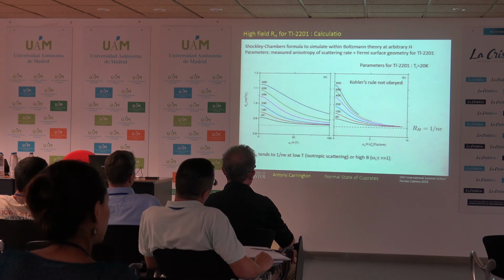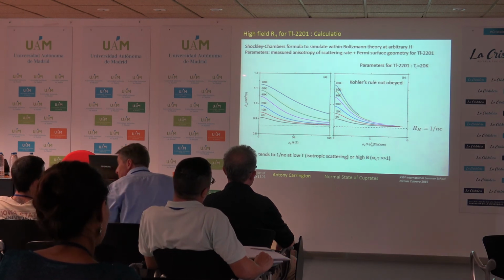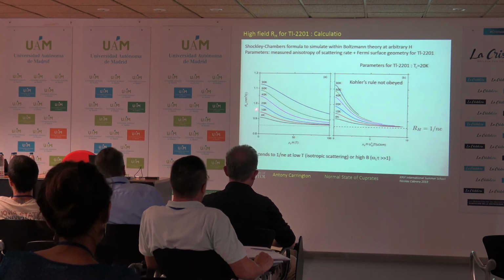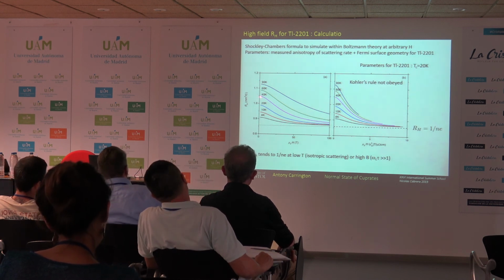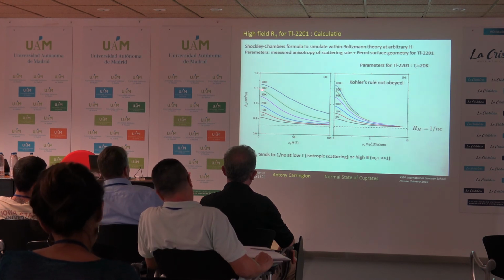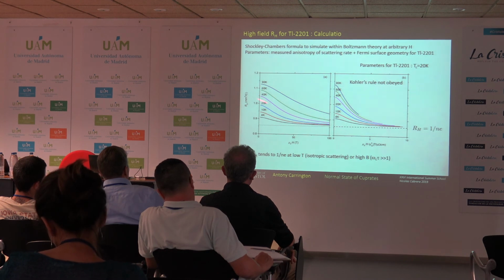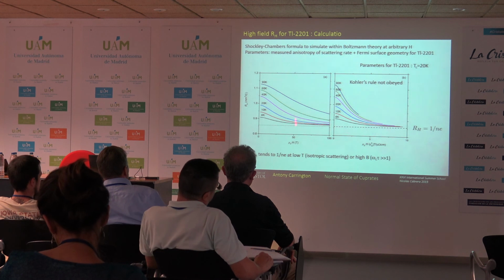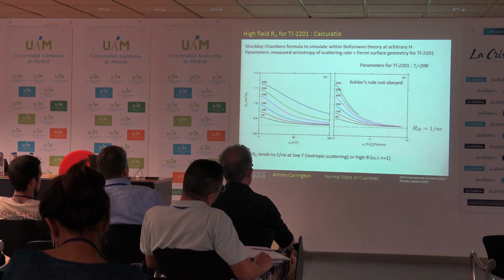Okay, so what happens at high field? At high field, what you find is that the Hall coefficient is field dependent. So this is a simulation up to 100 Tesla. And essentially, as you'd expect, as you get to higher and higher fields, you asymptotically approach 1 over ne. Okay? So these are values in simulation exactly for Tl-2201.